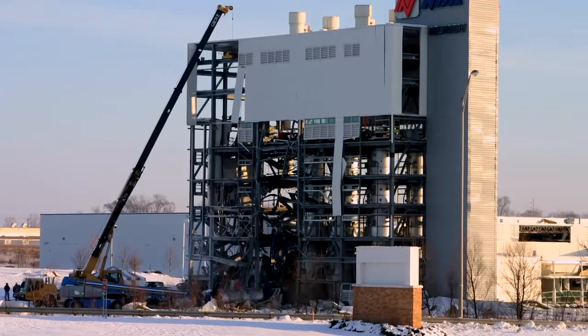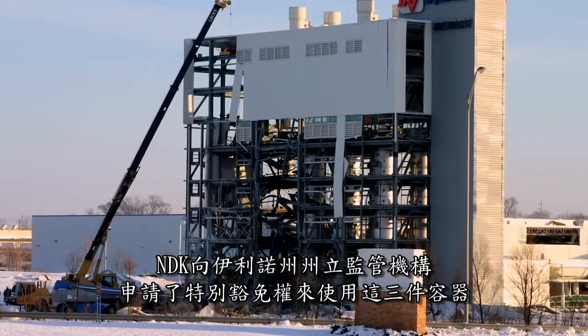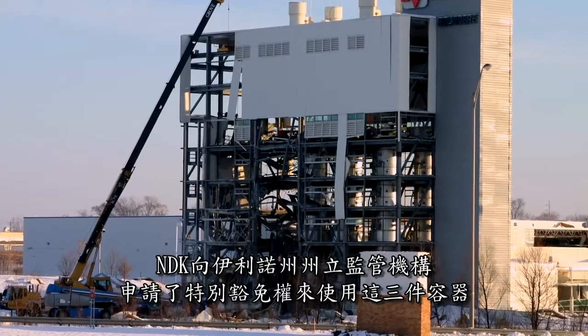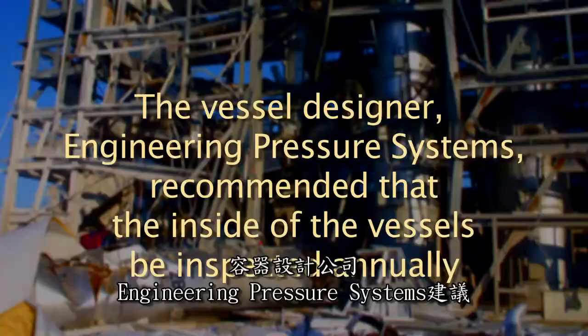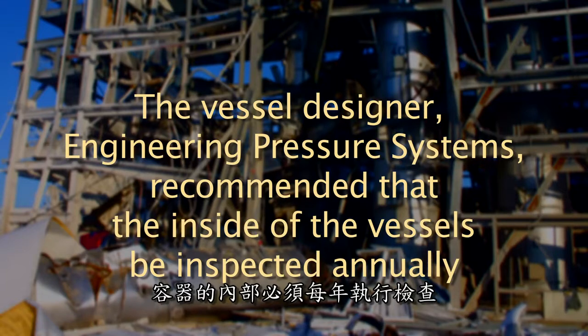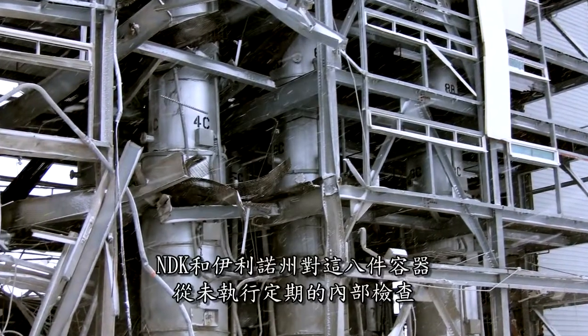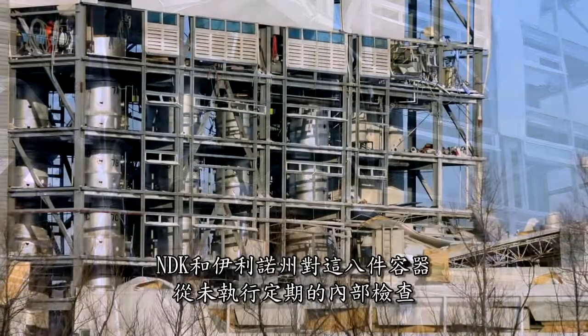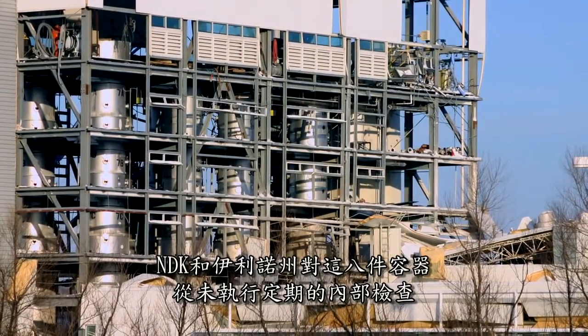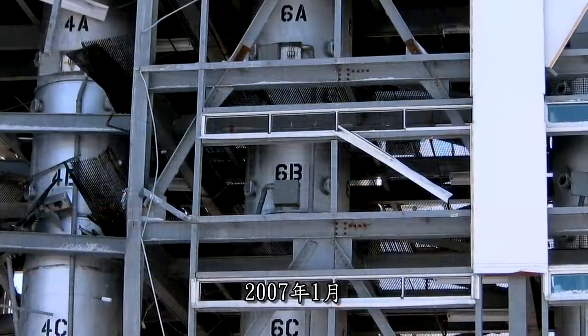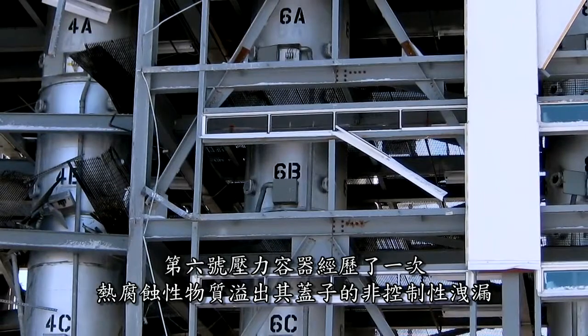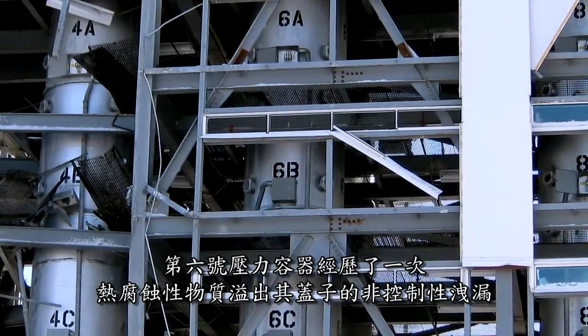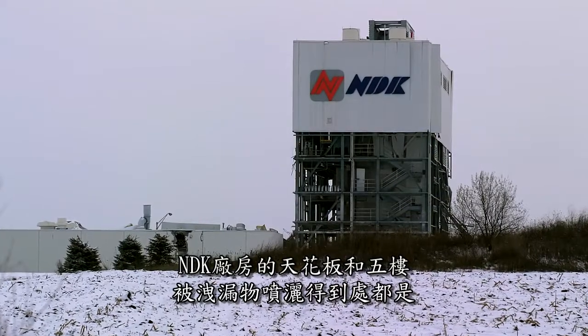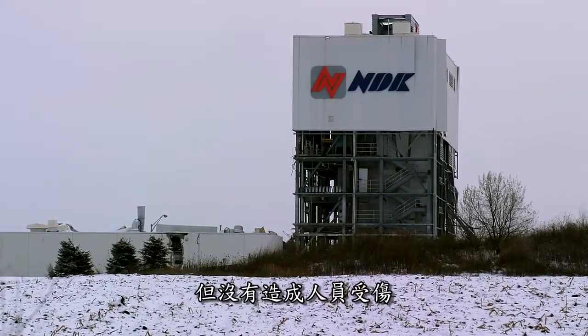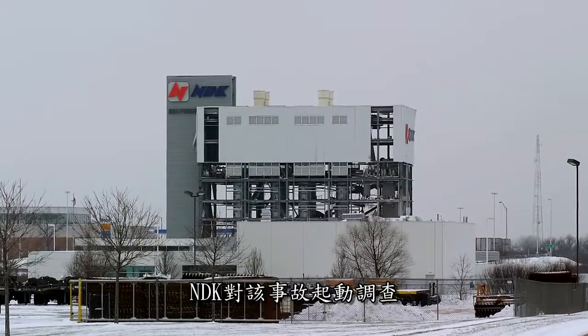In 2002, NDK had petitioned Illinois state regulators for a special exemption to use the 3 vessels, and this was granted. The vessel designer, Engineering Pressure Systems, recommended that the inside of the vessels be inspected annually, but the CSB found that neither NDK nor the state of Illinois ever performed regular internal inspections of any of the 8 vessels. In January 2007, pressure vessel number 6 experienced an uncontrolled leak of hot caustic material through its lid. The leak sprayed onto the ceiling and 5th floor of the NDK facility, but caused no injuries. NDK initiated an investigation into the accident.